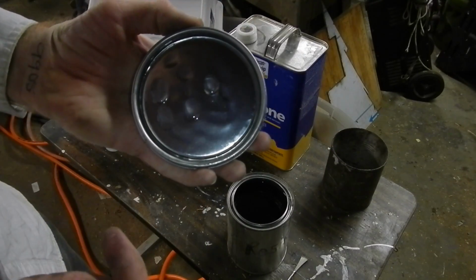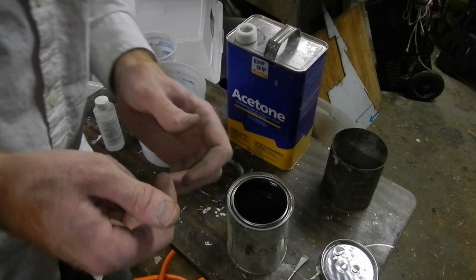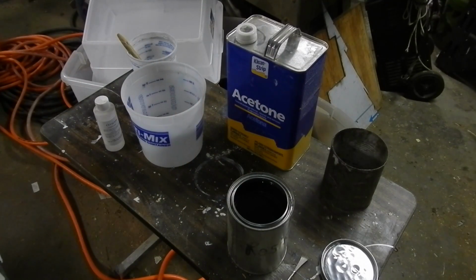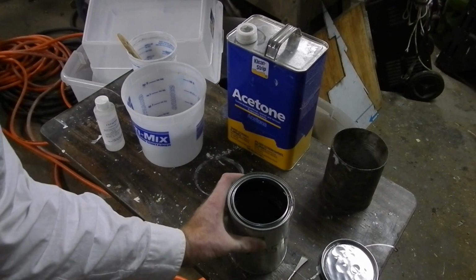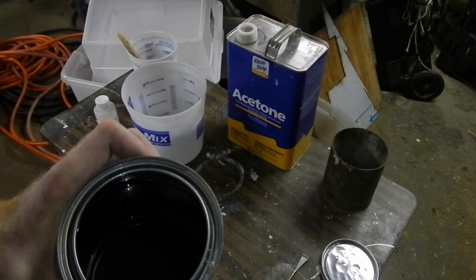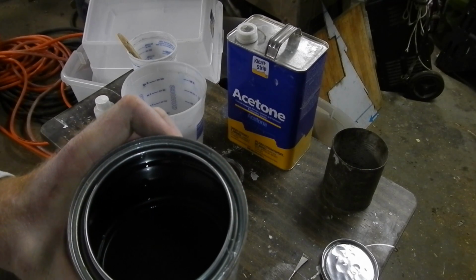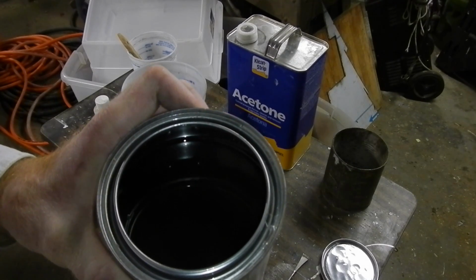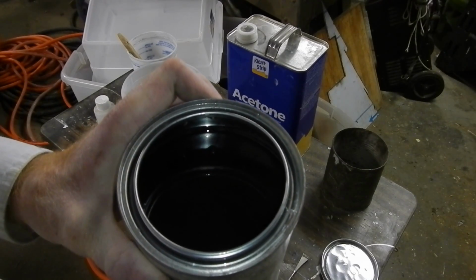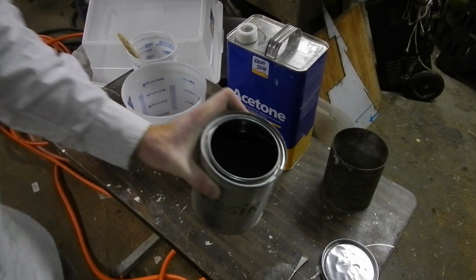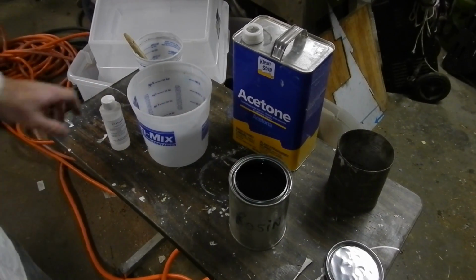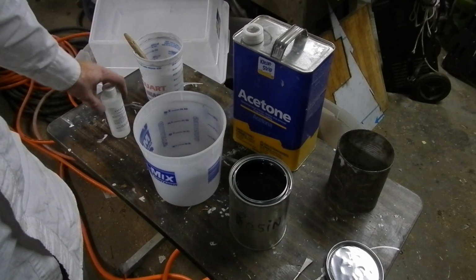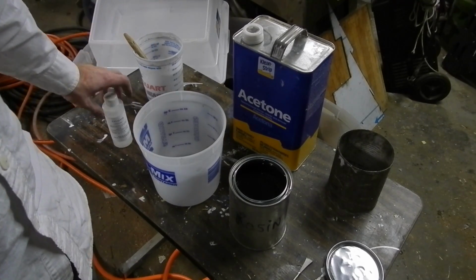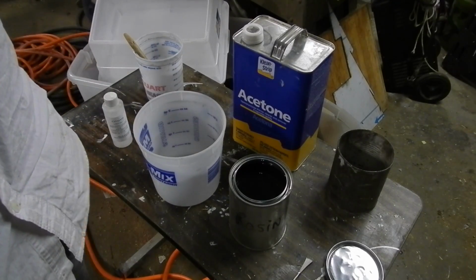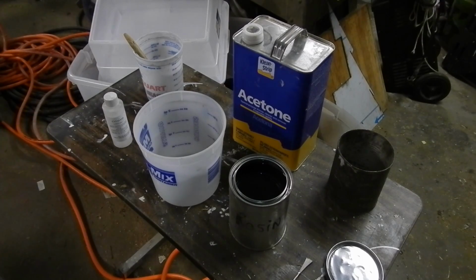I look inside my lid and I see that my resin has held itself well. I'm not losing resin because of any kind of chunkage or crystallization. Old resin, when it's been open to the oxygen and the open air, if it's sat long enough, will crystallize, and that means that the resin itself is no longer good. It won't cure. Even with your hardener, you can put as much as you want in there, and the curing will be sticky, and the quality of the repair will be much worse.